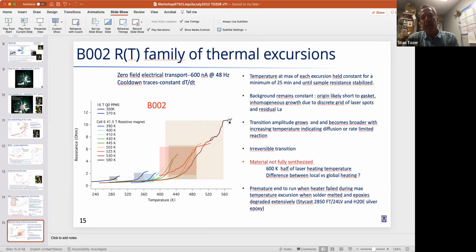The 580 is where everything failed. Solders failed, epoxies failed. They aren't meant to go that high in temperature. And we see that in this trace here where we are coming down, and the heaters which were soldered to the external wires, those solder joints failed. We lost continuity and the sample just ripped down. We also lost the sample because it also had solder joints on it.